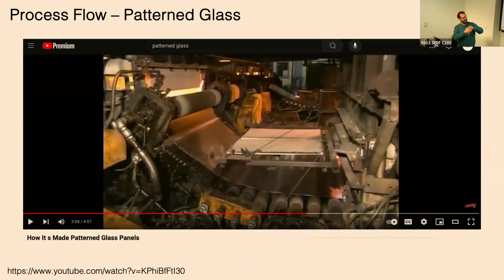But it does create that sort of structural glass that's in there. If you look at patterned shower glass or architectural glass, it will tend to go through this patterning process. Embossing as well, if you have leathers or papers, is a similar type of process. It then gets cooled down and made into mother sheets. It's worth a watch because it gives you a sense of how, from a glass perspective, hitting metal so quickly is just scary. You're cooling it down really fast. You're inducing a bunch of interactions between your metal drum that you're imparting your rollers on and the glass surface.